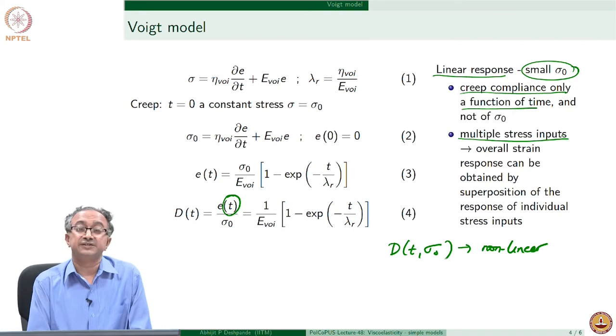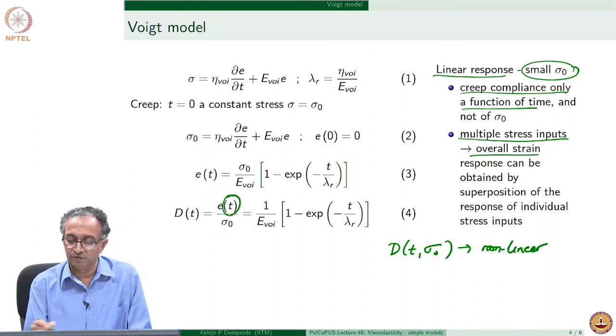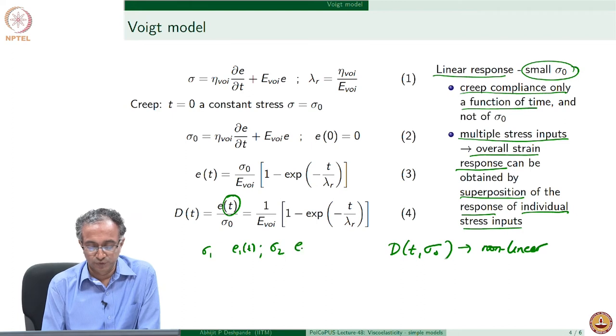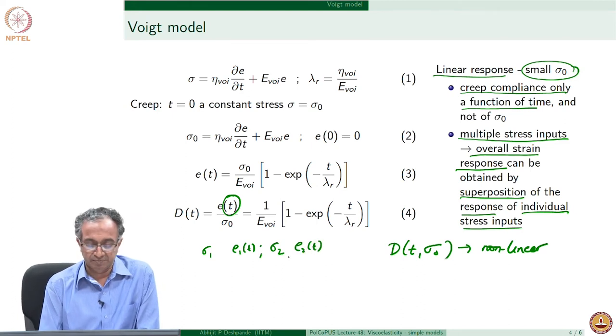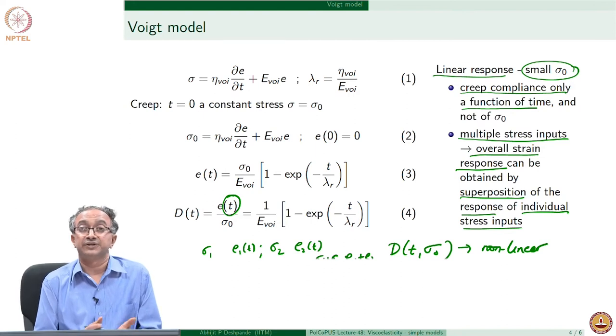If we apply multiple stress inputs, because it is a linear system — a linear ordinary differential equation — we can obtain the overall strain response by superposition of the responses to individual stress inputs. I can apply σ₁ and find ε₁ as a function of time, then apply σ₂ and find ε₂ as a function of time, and then apply σ₁ + σ₂ to get ε₁ + ε₂ as a function of time. This is called the superposition or scaling of responses.